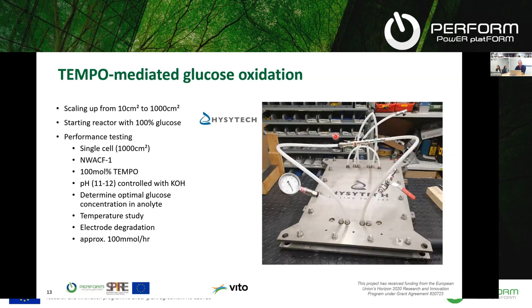From this small scale flow cell, we actually scaled up together with partner Hysytech to a 1,000 square centimeter cell, which was constructed by Hysytech. So this is a single cell that we used for testing, and which is also basically the blueprint for the pilot reactors. So we started with 100% glucose addition, so no introduction of any impurities at this point. And we did performance testing with the non-woven activated carbon fiber. We used in this case 100% tempo, and we determined the optimal glucose concentration in the anolyte.